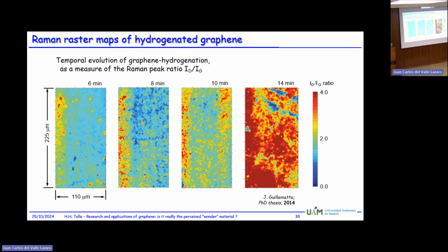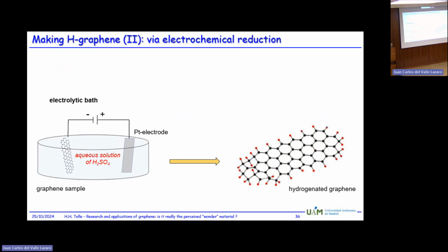And you see here a series where, from very few hydrogen atoms exposure, it gets higher and higher. So more and more hydrogen is absorbed on the sample. Now here we did not have such a hydrogen generator available, which costs something like 20,000 euros or so. So we did something which chemists in the lab tend to do. They use an electrolyte in a bath, put some electrodes into it, and let a chemical reaction happen. And exactly that is what we tried as well.